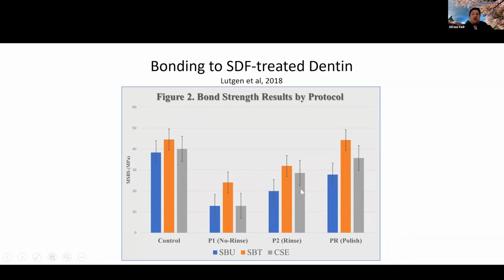After you completely rinse it off, you could use total etching technique or a two-step self-etch. But it was way better if we could remove the superficial discolored dentin. We could get a much better bond strength. But the reality is that this was done on sound dentin, right? And that is really not the clinical substrate that we usually have when we're bonding to SDF treated dentin. Usually our clinical substrate is caries affected or even infected dentin.